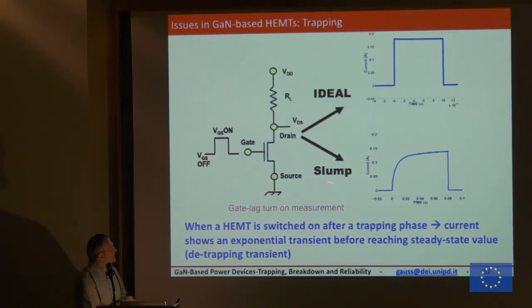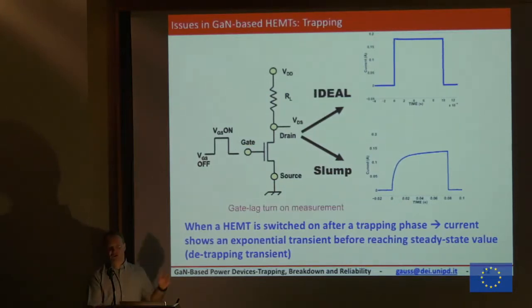This is what happens. The current goes up not as fast as I expected, but it is going down very slow. This is a real measurement we have done maybe 15 years ago. But if you look at the time scale, this is not an error. This is real. This is second. So this is 0.1 second, 100 millisecond. And this is 20 milliseconds. So the device takes more than 20 milliseconds to reach regime.